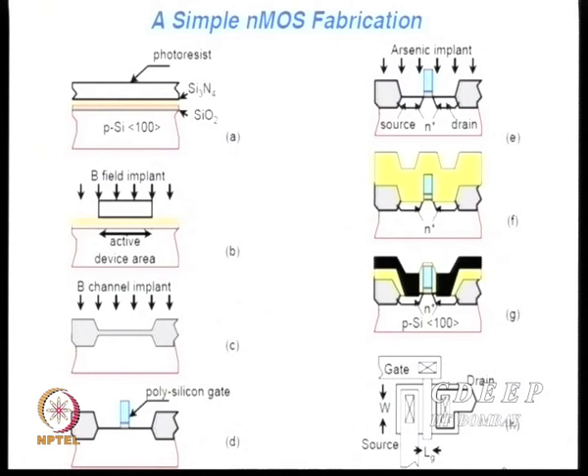Areas where something should happen are protected; areas not needed are etched out. Using the resist, boron implants are done — boron cannot penetrate the resist, so it goes only into the open areas. These P+ areas are called channel stoppers, and the first masking step creates them.